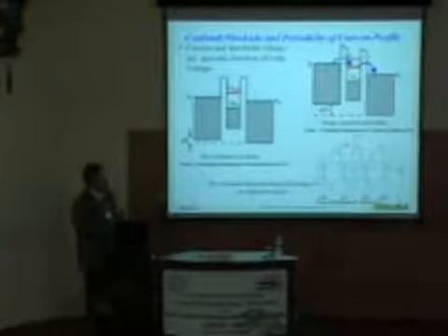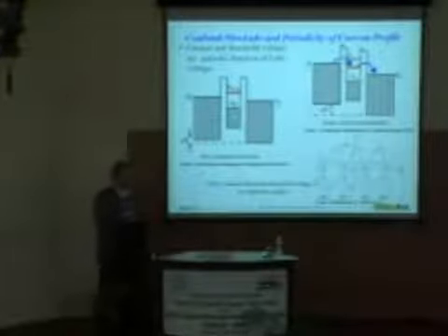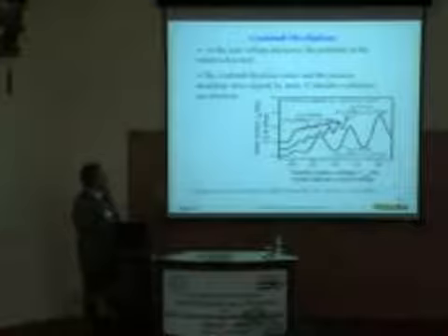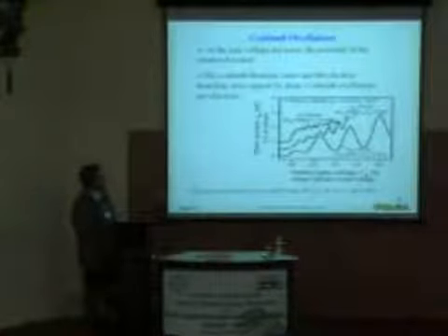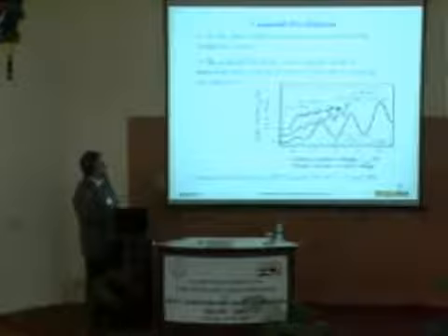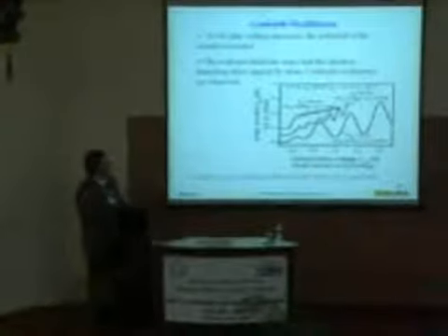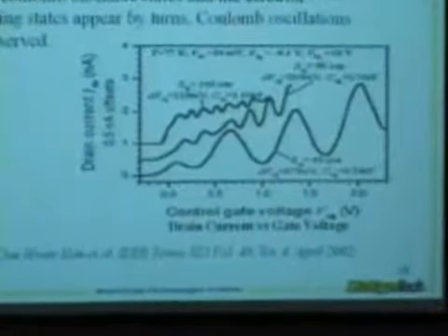Characteristic of these devices are regions at which current can significantly conduct and regions where current does not conduct. So as you adjust the gate voltage, you tend to see regions where you have spikes in current and other regions where you basically have nulls in the current, related to the energies of the available states. This is borne out in what's called Coulomb oscillations in the output drain current as a result of sweeping the gate voltage for various drain source biases. This is an example of that for different conditions. This device in particular was measured at 77 Kelvin. And the characteristic widths and heights of the current spikes that you see in the Coulomb oscillations are representative of the energies in the system. I think I'll choose to skip this for now.